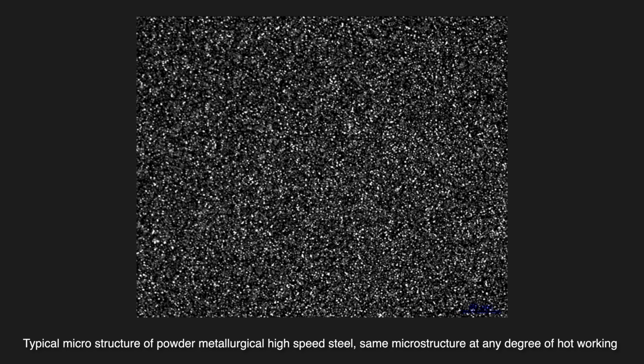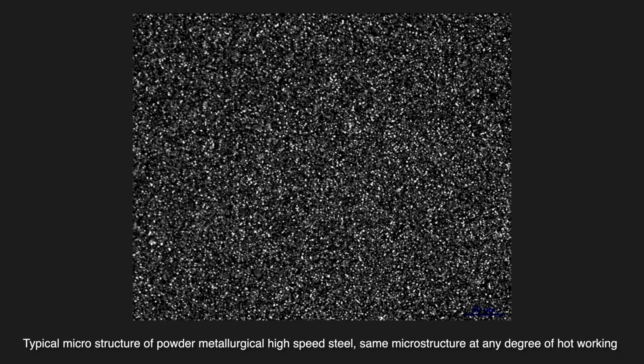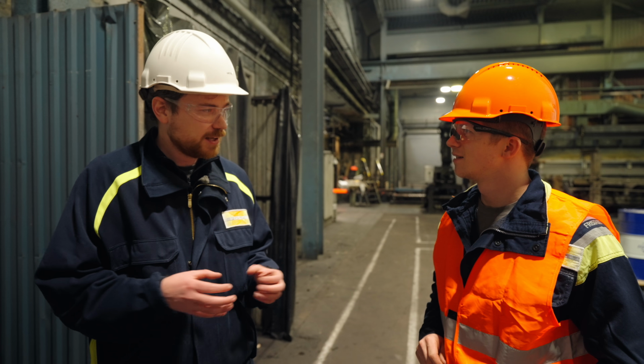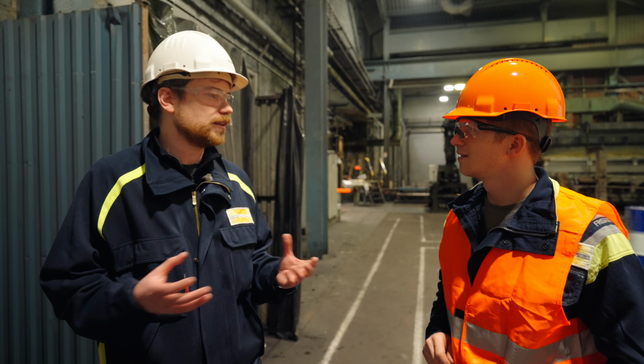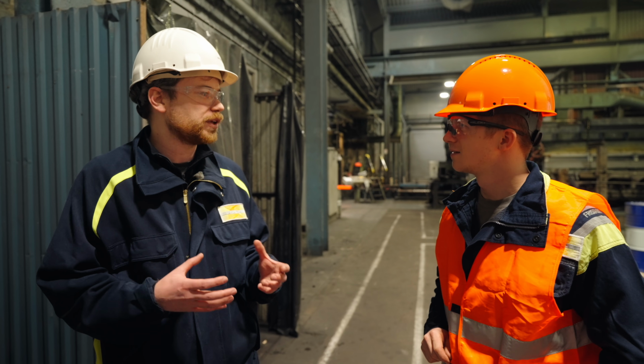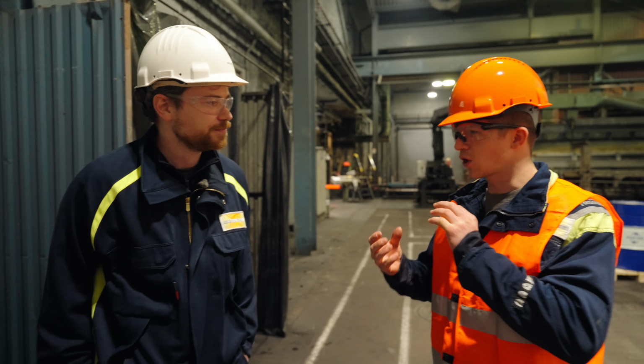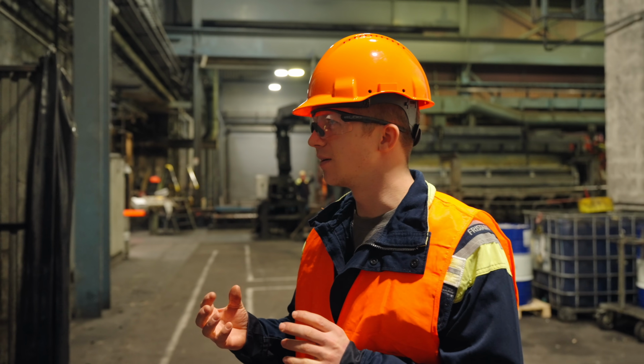But when you make it into powder, you get such a fine distribution of all the alloying elements within the steel, so you sort of regain a lot of that toughness into the product, and you can actually forge and hot work it. And so, for context, when you say highly alloyed,